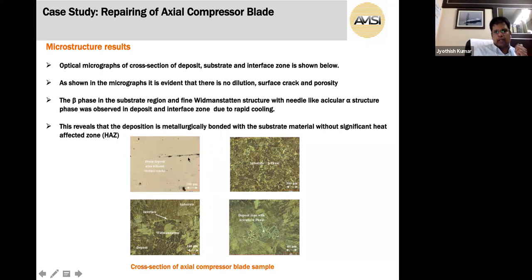As you can see, this is the dense deposit area without surface cracks. There's also the complete dense deposited area without cracks, without pores. And this is the substrate portion. When I say substrate, substrate is the base material, that is the blade, where we have deposited the same material. And this image clearly shows the Widmanstatten structure with the deposit, the interface, and the substrate. It completely looks like a single material with the clear Widmanstatten structure, where the deposited material is completely bonded with the base material.